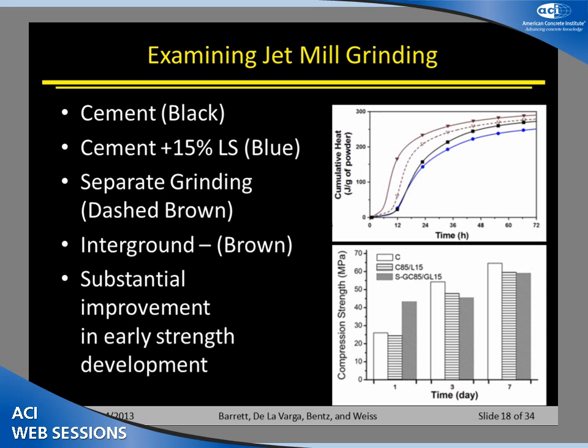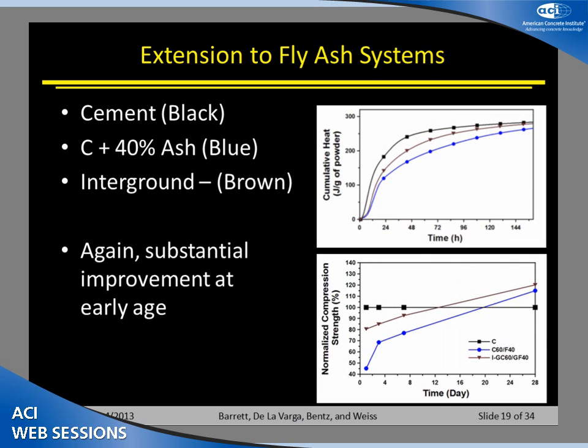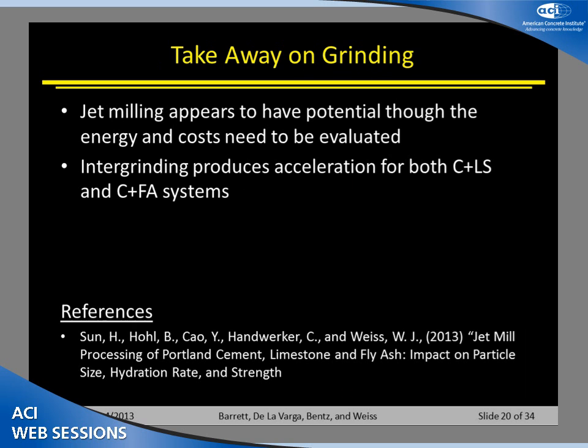So by intergrinding, just like we see in a ball mill or in other technologies, the limestone gets preferentially smaller than the clinker, and we can see some real benefits there. Again, the benefits are really coming at early ages, and that's very important for a lot of these higher volume fly ash systems. Again, to extend this to fly ash systems, here we've got the cement, the ash, and the interground system shown in brown. If we intergrind, we can increase that heat, and again the strength, we can start to get similar properties at earlier ages through that intergrinding approach.